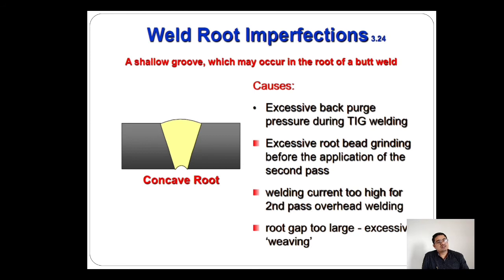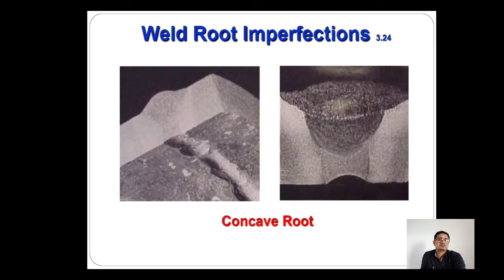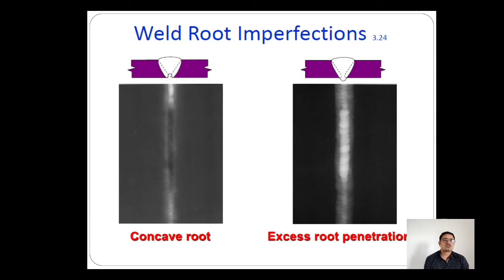And the fourth one is root gap too large. If the root gap is too large, with excessive weaving, then you can find such a discontinuity. So friends, in macro you can observe such a figure. And if we talk about radiography, on the very left side you can see the concave root. In the radiography, the center portion of the bead will be darker in density in the radiograph, and that is called concave root.